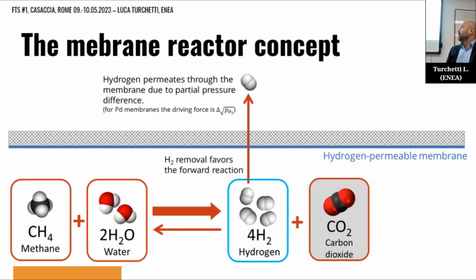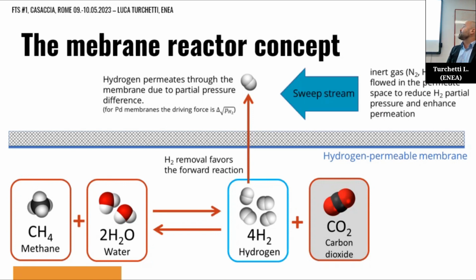In order to enhance hydrogen transfer across the membrane, it is not necessary, but usually you also include a sweep stream, typically steam, or you can also use nitrogen, but it would be difficult then to separate the hydrogen from the nitrogen. This way you can achieve high conversions also at lower temperatures.